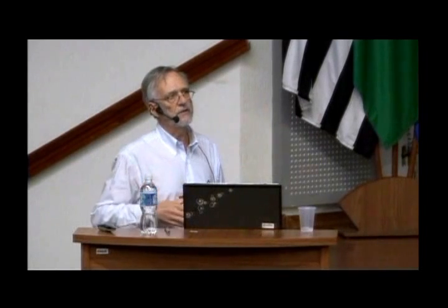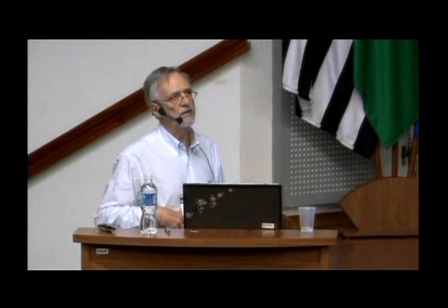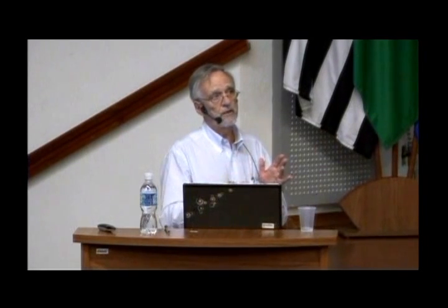But if we go too much larger, then we lose a lot of the nanoparticles in the reticuloendothelial system, in the liver and the spleen. It's really a balance between how long the nanoparticles can keep circulating and what the avidity of the nanoparticle for the target is.